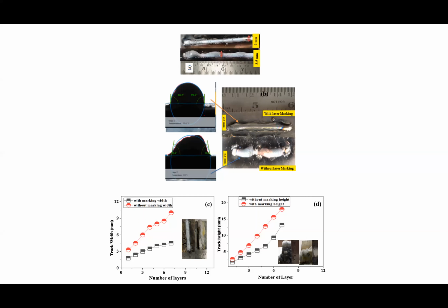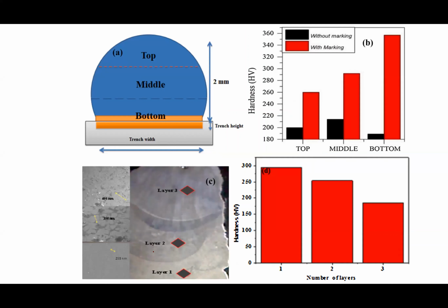So the Ni concentration in the NiTi wire used for the VAM sample was 55.9. Therefore, the composition after the second layer was close to the composition of the initial wire with or without the laser marking. On the other hand, the Ni concentration in the first layer was lower than the wire without the laser marked samples. So this is the layer which we are trying to get. So we try to build the layers.